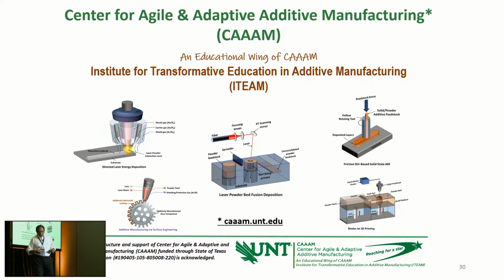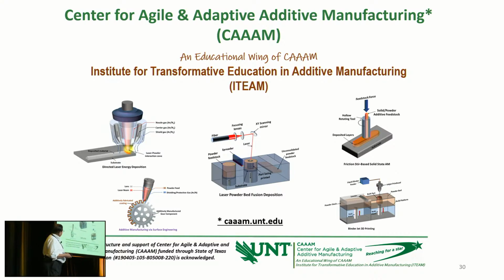Then this is surface modification. You don't have to build the AM component from the bottom up. You have an existing component, and on top of that component you can deposit new material layer by layer to get the required properties. And this is a solid state AM process, where you use friction stir welding to weld material layer by layer on top of each other to build the component. Each one of these will have different thermokinetics, and accordingly you have to modify the equations to predict the thermokinetics of the process, and then predict the microstructure as well as the phase structure in the material.